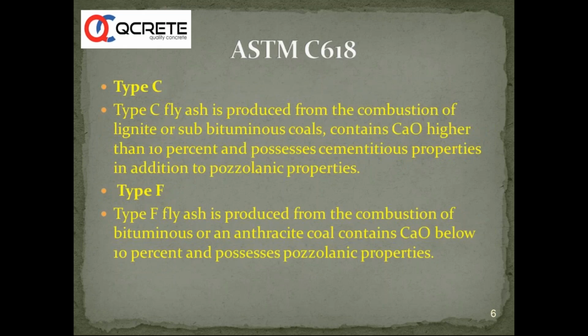Whereas we have other classifications from ASTM where it is classified as Class C and Class F. Class C is where the CaO content is higher, and it comes from subbituminous coals. Class F is where the CaO content is lesser than 10%, and it comes from combustion of bituminous coals. Predominantly in India, most of the thermal power plants are using this kind of coal, and hence we get more of type F fly ash. Type C fly ash is not abundant in India.